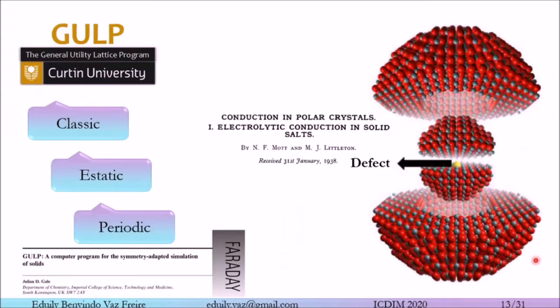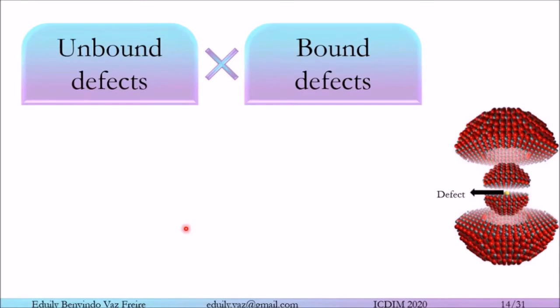For the inclusion of defects in the matrices, we chose the Mott-Littleton method, which divides the material into 2 concentric spherical regions where the center is the defect, and we optimized our structure based on the defect. Our calculations were performed using the GULP program, which is a classical calculation program, and were performed in a static and periodic manner.